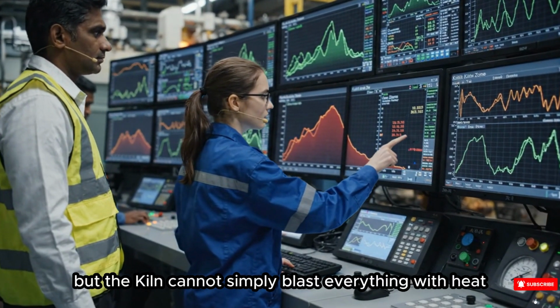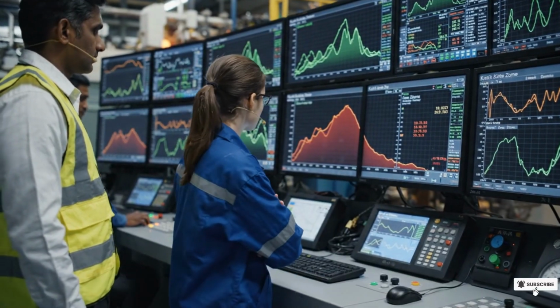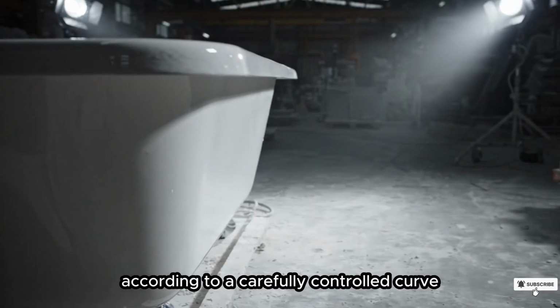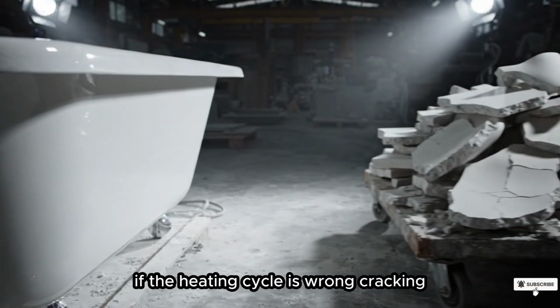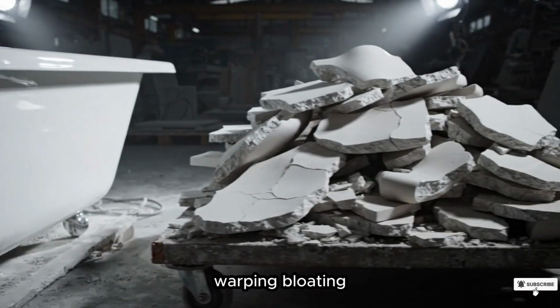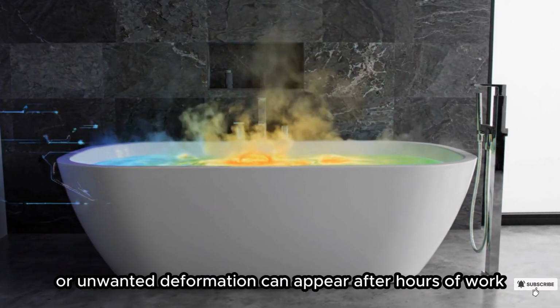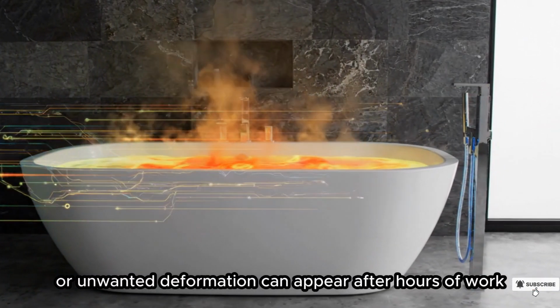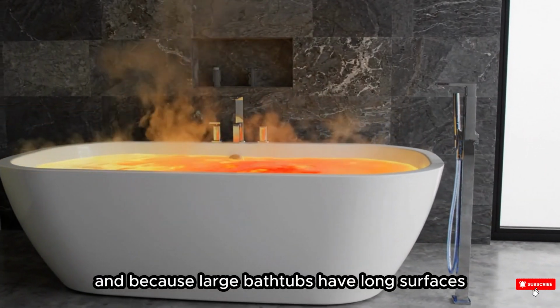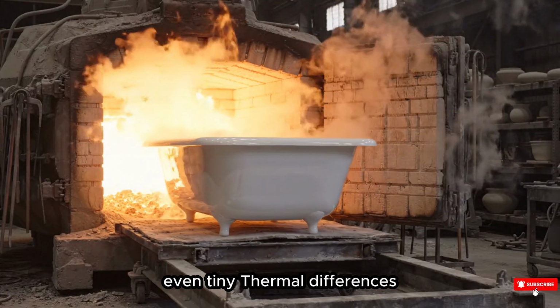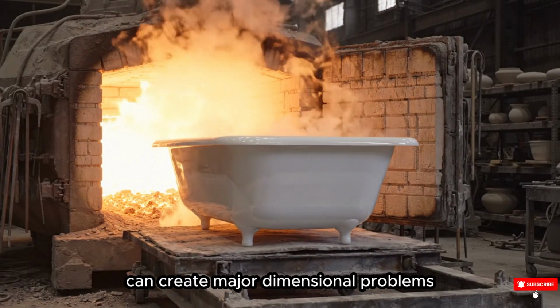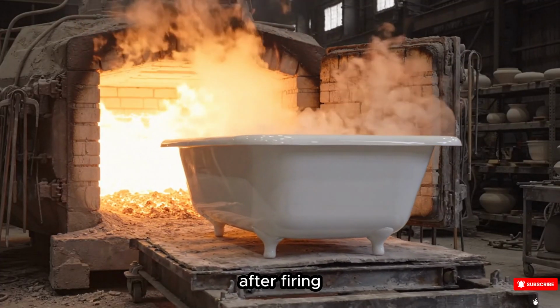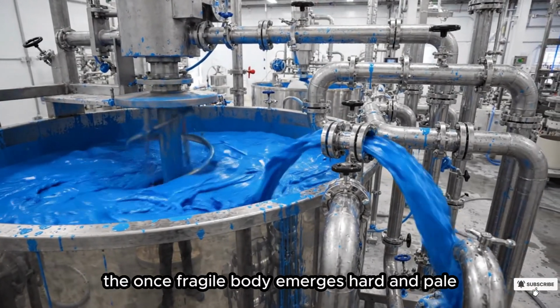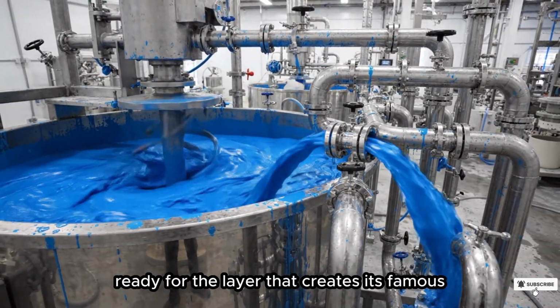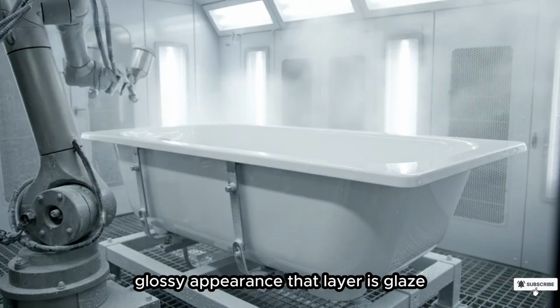But the kiln cannot simply blast everything with heat. Temperature must rise and fall according to a carefully controlled curve. If the heating cycle is wrong, cracking, warping, bloating, or unwanted deformation can appear after hours of work. And because large bathtubs have long surfaces, even tiny thermal differences can create major dimensional problems. After firing, the once fragile body emerges hard and pale, ready for the layer that creates its famous glossy appearance.